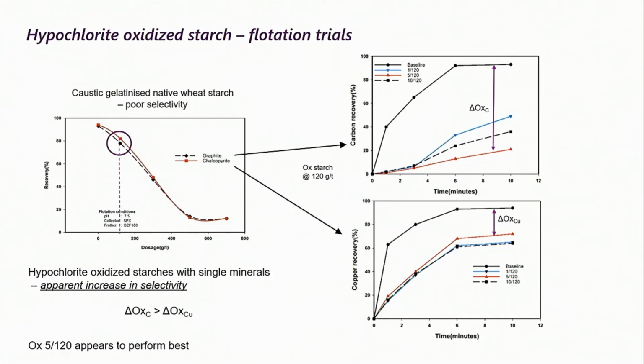Over on the right there, we've taken it at 120 grams per tonne, and you can see the blue is the 1%, the red is the 5%, and the dotted line is the 10%. And you can see that in between there, that red at 5% of the hypochlorite, we're getting quite a good difference between the depression of the carbon versus the depression of the chalcopyrite. So that sort of indicated, from an initial trial, that there's a possibility of being able to improve the selectivity.